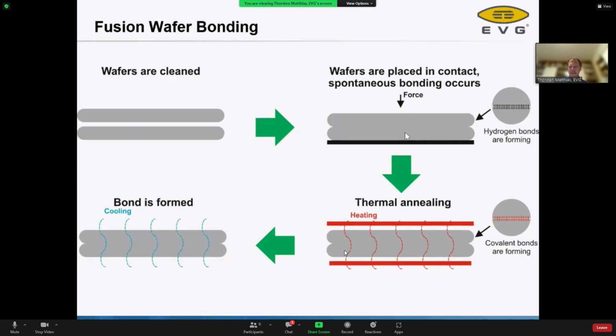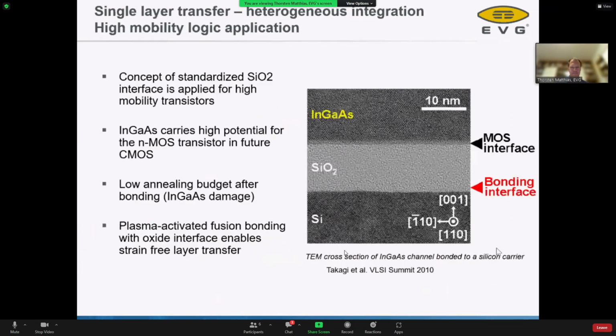So the bonding itself happens at room temperature. Initially, I create some hydrogen bridge bonding, but during the annealing process, this is transformed into a full-area covalent bond between the two wafers. Now, this can be used for any kind of materials, any kind of wafers or semiconductors that I can integrate by fusion bonding. As long as I can deposit a dielectric on a wafer and I'm able to polish it very well, I can use this to transfer layers of one semiconductor to another. Here we see an example of indium gallium arsenide transferred onto silicon, but it can be used for all kinds of materials.